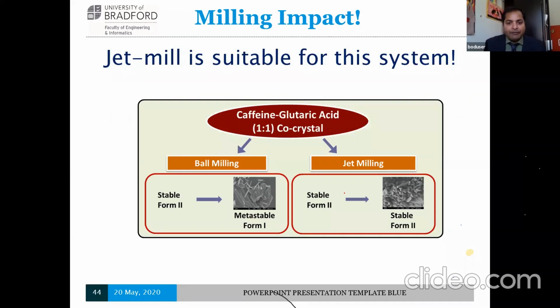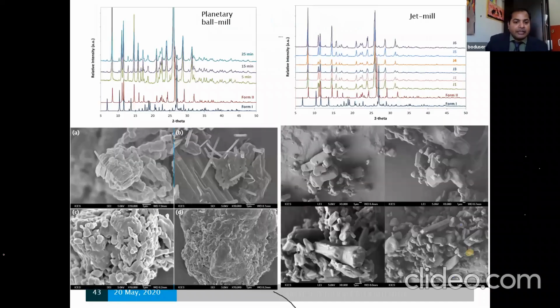And if you look at ball milling, you could see metastable formation. And in the jet milling, form 2 was stable through the entire micronization process. We also proposed the mechanism of the planetary ball mill. I would refer back to this particular slide. By increasing the time of milling, agglomeration was seen. We proposed a mechanism that by increasing the temperature at the local surface, it is probably already reaching the temperature for the melting of this co-crystal on the surface, and this started coming together and forming agglomerates.